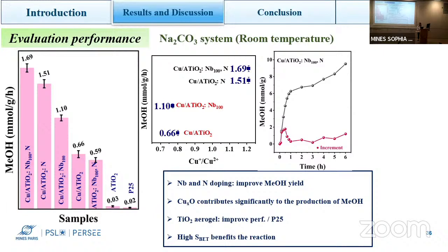When we increase the quantity of copper at the beginning, it stays at a good oxidation number, but when we increase the quantity, we observe at the end a reduction, probably due to the alcohol or maybe to the alkoxide group in the solution.